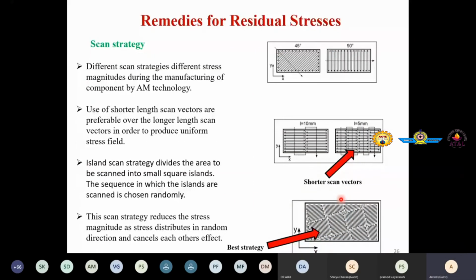So some remedies for residual stresses during the process we can adopt, like we can design the scan strategy in a proper manner. Different scan strategies are available, and each gives different magnitudes of stresses in the part. For example, this scan strategy you can see is inclined 45 degrees, this is 90 degrees. Then another is shorter length of scan vectors like this, and even shorter length of scan vectors, right? Use of shorter scan vectors is preferable over longer length scans, so that the temperature gradient is reduced and restricted to a small zone only. So it will produce stress variation locally.